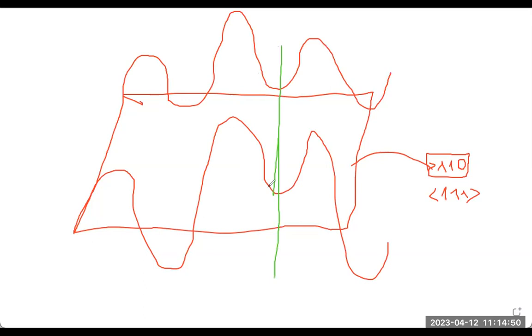So they can locate at discrete energy states. So this is one energy level. These are all different energy levels. And this screw dislocation wants to jump from this energy state to this, the lower energy state. Its core is compact core, not planar core. So it is really hard to activate the motion of this screw dislocation.